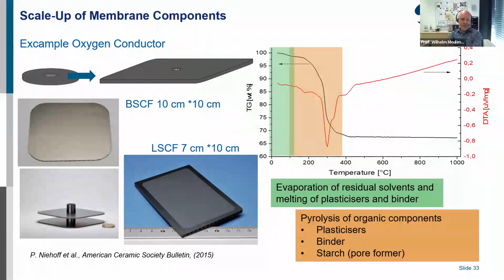That means what is of interest for later maybe commercial applications, and then we scaled up first to 10 by 10 centimeter. That is in this case, for example, an LSCF or a BSCF membrane with a different membrane design. And if you then use the same temperature and sintering program as for the 15 millimeter membranes, you produce only rubbish. The membrane is completely destroyed. And the reason for this is you have here a larger volume of membrane which you have to sinter.